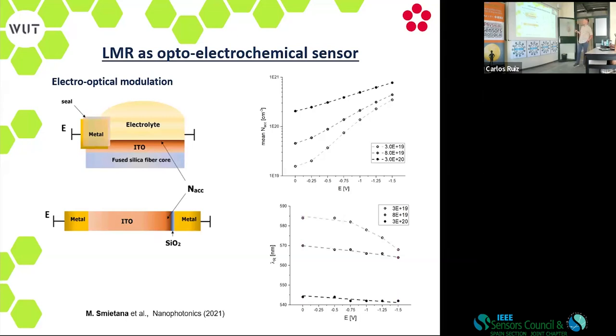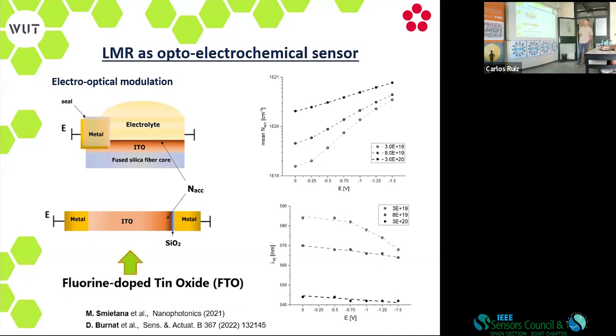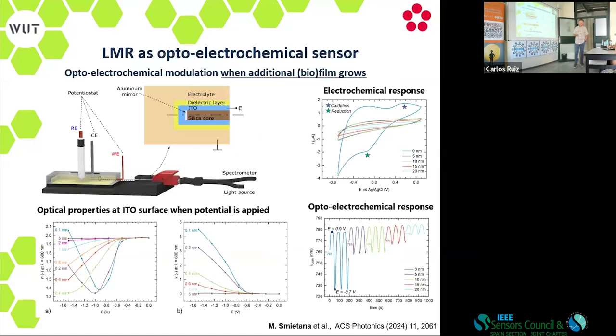So just playing with the potential can tune this number of charges in the accumulation zone, and we can tune also the ability of the system for being used as an optical sensor. So also in time we tested different materials. One of them is fluorine-doped tin oxide (FTO). It may work similarly to that, with a slightly different value. So just very recently, we noticed that this material is actually quite good for laboratory biosensors.